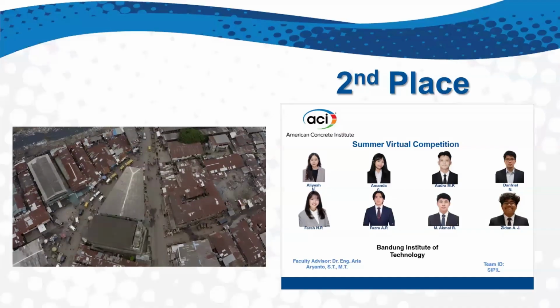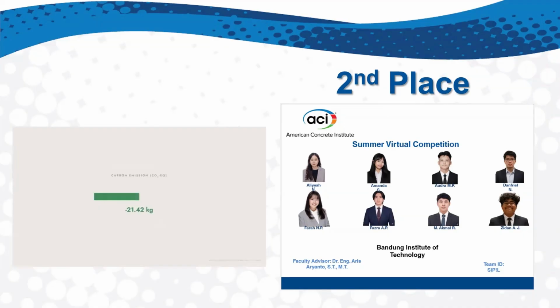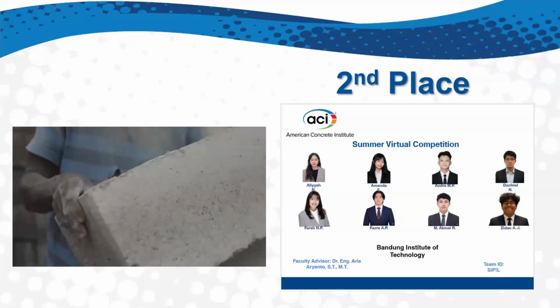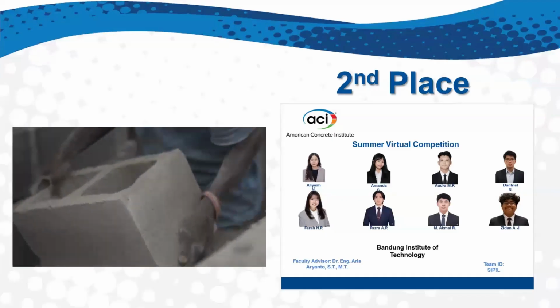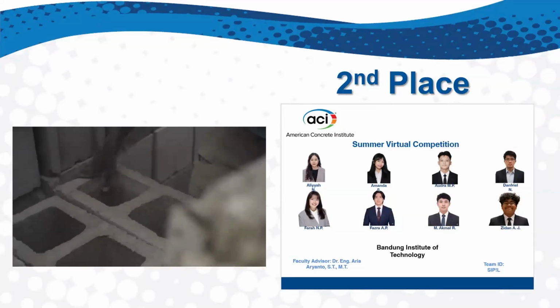But does it work? A life cycle assessment study conducted in Singapore shows this process achieves negative 21.42 kilograms of CO2 equivalent per ton of RCA. This is carbon negative concrete. On a global scale, this approach could deliver up to 0.64 gigatons of carbon dioxide equivalent reduction per year globally, contributing equivalent to 10 to 35% of the Paris Agreement's negative emission target.